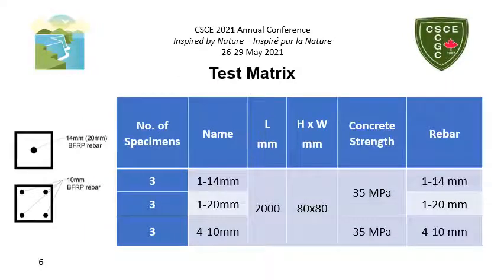The test matrix consists of 3 specimens for each of the 3 rebar configurations. So there are 3 specimens with one 14 mm BFRP rebar located in the center of the post cross-section, 3 specimens with one 20 mm BFRP rebar also located in the center of the cross-section, and lastly 3 specimens with 4 10 mm BFRP rebars, one in each corner. The concrete was cast from a ready mix with a specified compressive strength of 35 MPa. The specimens measure 80 mm in width, 80 mm in depth, and 2000 mm in length.